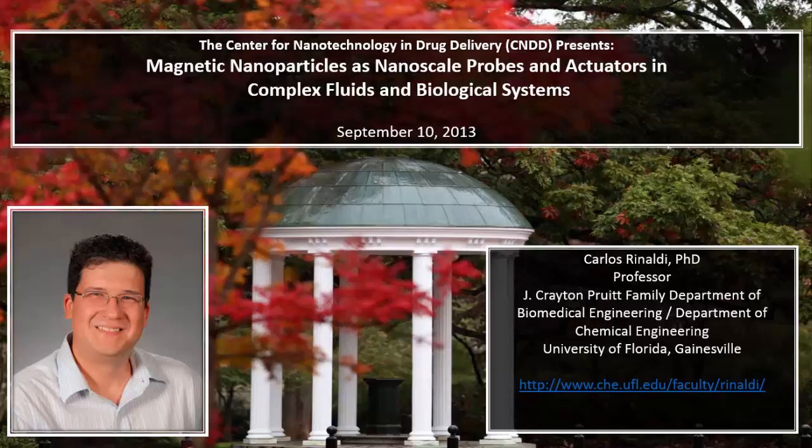So before I go on, the applications that I'm going to talk about today take advantage of the response of magnetic particles to time-varying magnetic fields. And I want to point out that there are two ways in which particles respond to a magnetic field. One is you have a particle with a magnetic dipole, shown in green, and you apply a magnetic field in a certain direction, and the particle physically rotates so that the dipole aligns with the magnetic field. This is what's called Brownian relaxation. The other possibility is that you apply the field, and the dipole physically rotates within the particle without physical rotation of the particle itself. And this is what's called Néel relaxation.